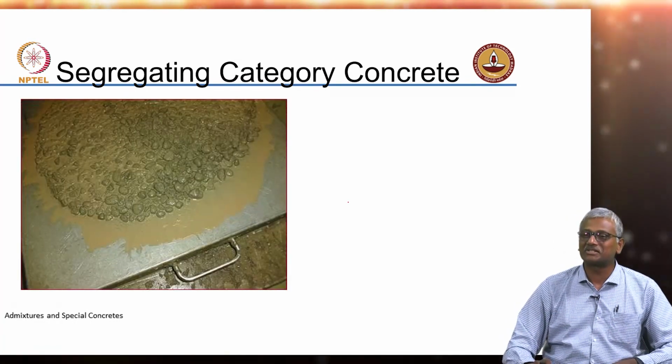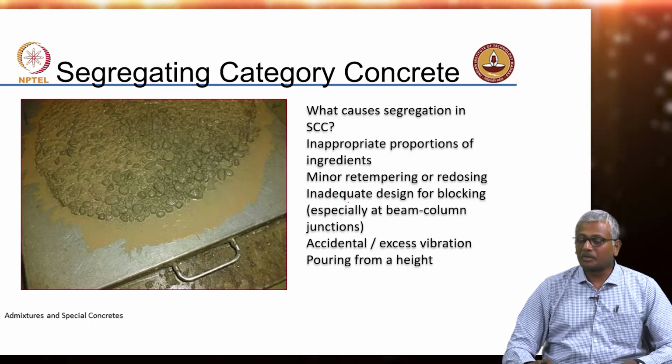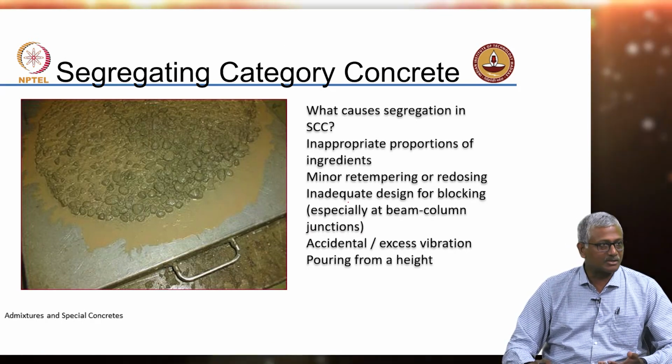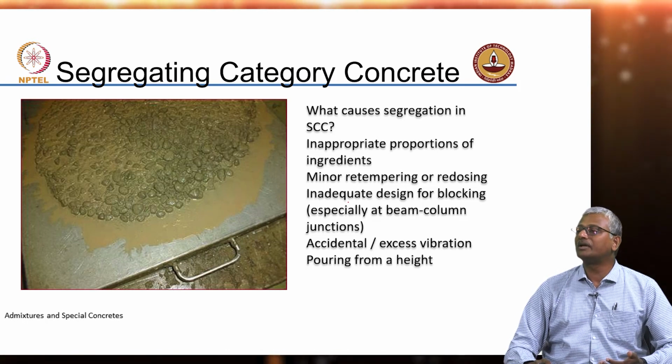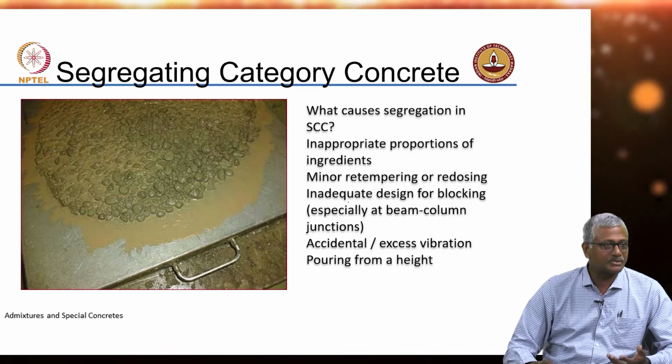Of course, segregation is a realistic possibility with SCC if you don't design well. Inappropriate proportions of ingredients can cause segregation. In your attempt to provide very high flowability, if you increase water content too much, it can lead to segregation.